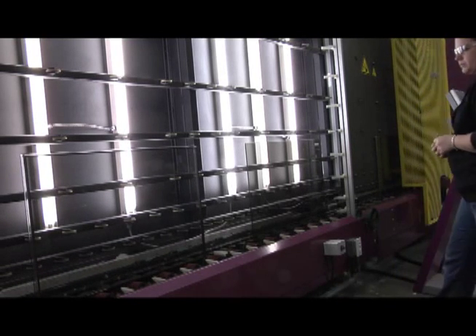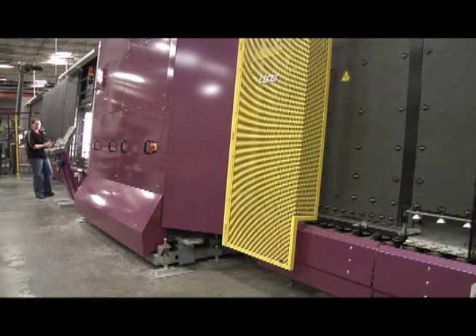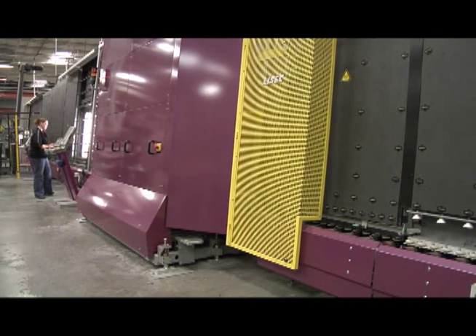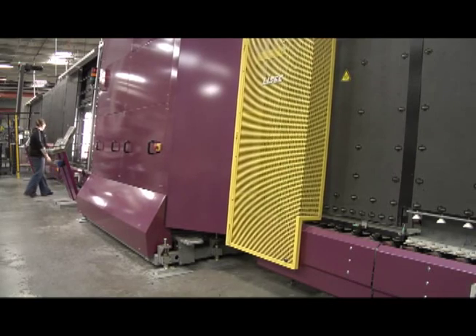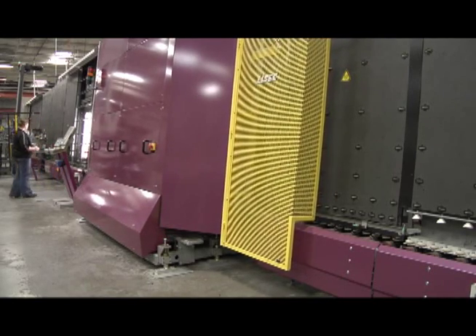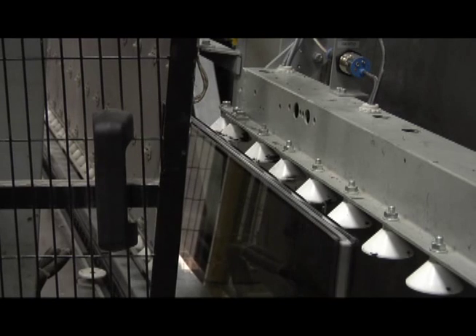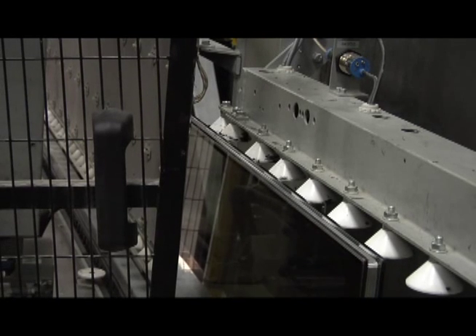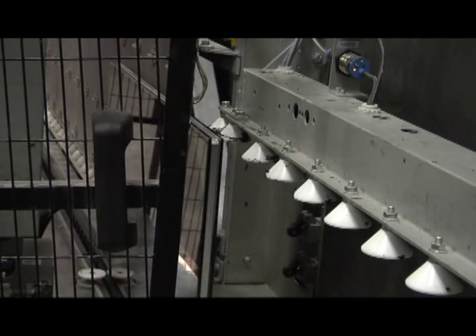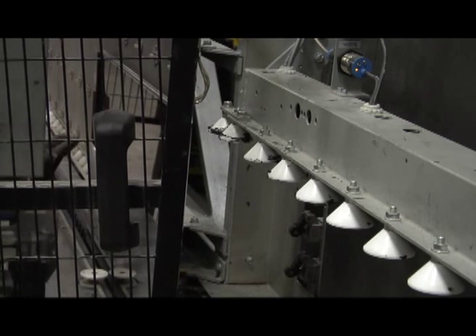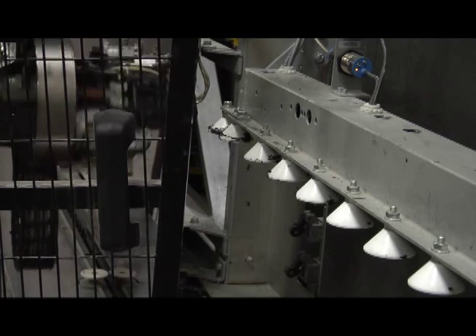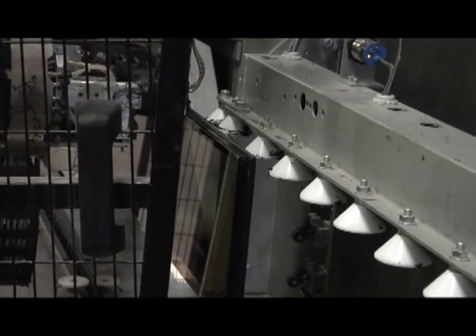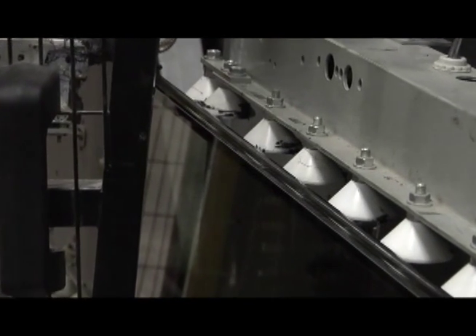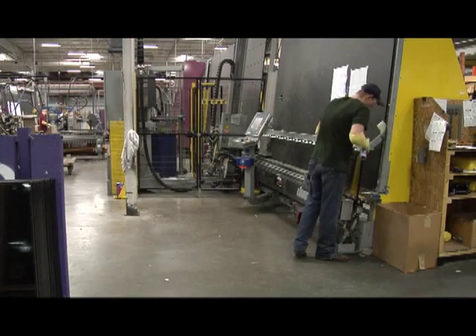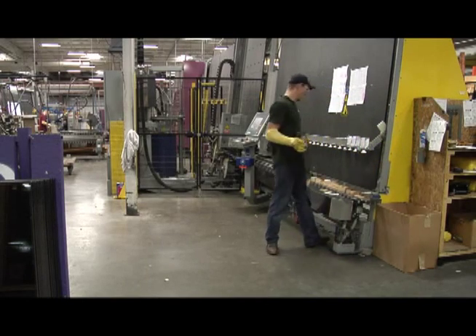Next, the glass is married together in the argon gas-filled pressing chamber. This allows argon gas to be inserted inside the glass without the aid of spacer plugs. The third and final structural seal is robotically applied at the end of the process. Manko was the first domestic manufacturer of EdgeTech's Tri-Seal automatic application. We have been tested and certified under the ASTM E2190 standard, including argon gas retention. This ensures quality assurance to the specifying designer.